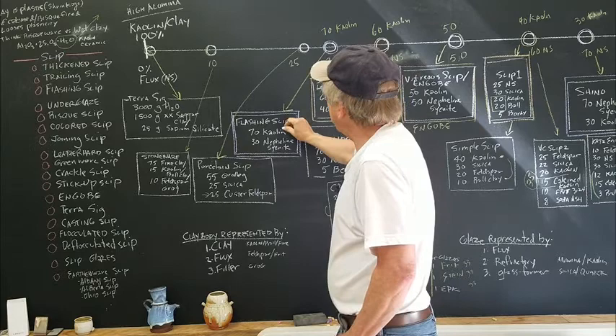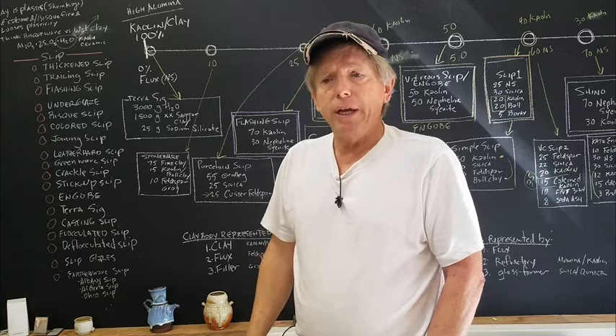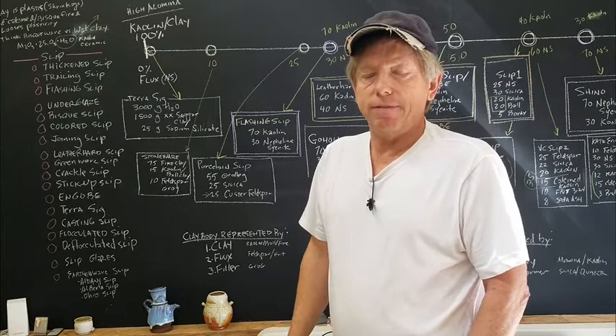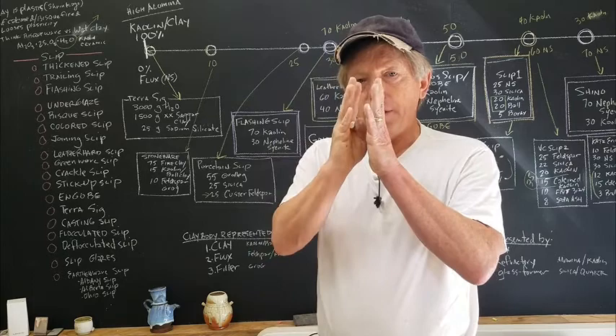Now you can vary the kaolin with Helmar or Grolleg or Tile 6 or something. In the old days we used Avery and that flashed a certain way, so you can change the way it flashes and change maybe the type of flashing. But the idea is there's a lot of clay in there, 70%. So when you put that on a bisque pot, which will not shrink, and the 70% clay tries to shrink, it'll crack off.